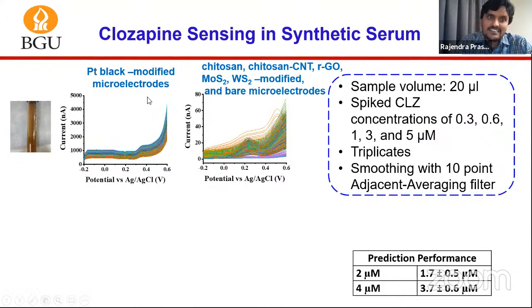Here you can see this data, I actually separated it because in the modifications that I have shown you, there is a modification called platinum black, which has a very high electroactive surface area, and that is giving very high current. So in order to visualize them clearly, I separated them. This was also a limitation of the machine itself, because when you record them together, this signal acts as noise for the other electrochemical signals. So we recorded them separately just to have a clear electrochemical signature.